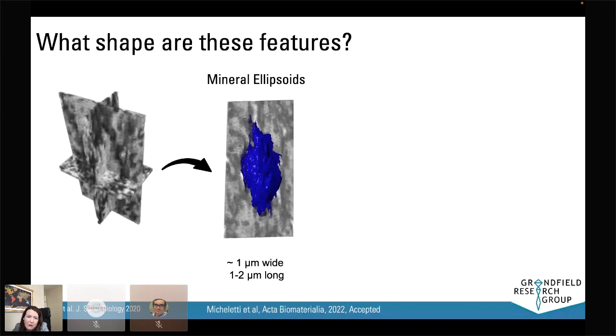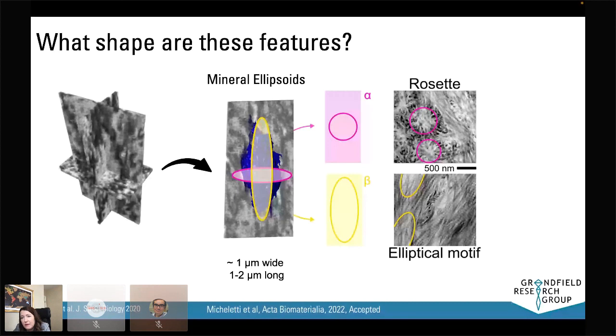These ellipsoids are about 2 microns long, 1 micron in diameter, and they were ubiquitous across our bone structure. This corresponds really well to things we've observed in TEM but didn't have the ability to view in 3 dimensions, such as rosettes, or elliptical type motifs down other orientations. So what we really show now is that there's this elliptical structure and clustering of bone mineral that was never observed before in 3 dimensions.